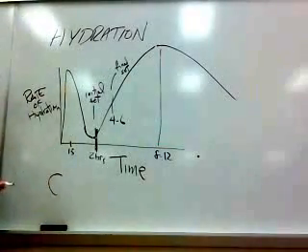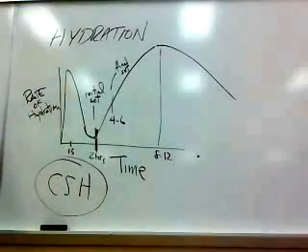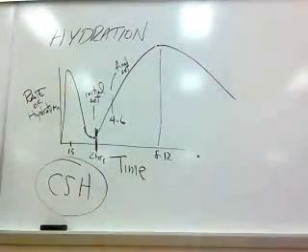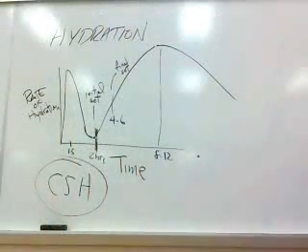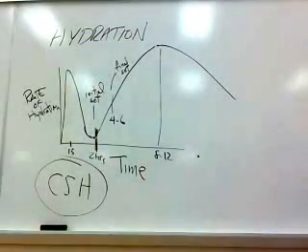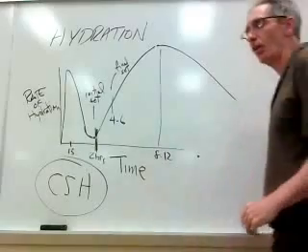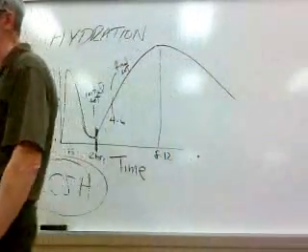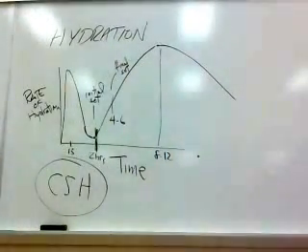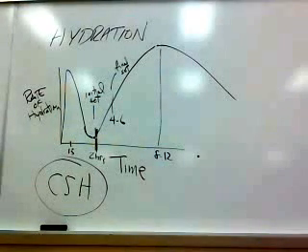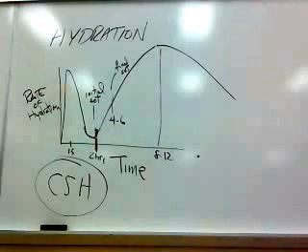There's a couple of crystals that form. The crystal that we care about is a crystal called CSH. And that crystal, CSH, stands for calcium silicate hydrate. Out of the matrix of all the crystals, this probably makes up 50% or more. And this is the good stuff. This is the really good stuff. CSH, you can think of, causes stuff to harden.